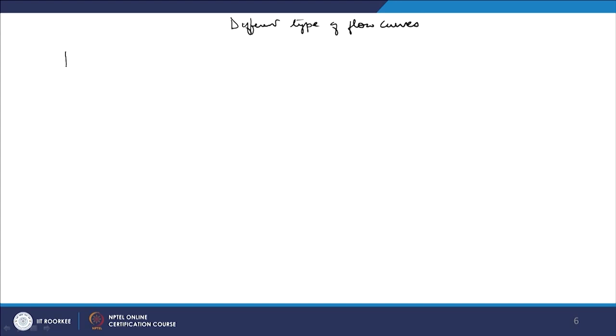So one we have already seen, at low temperature, sigma versus epsilon. You will have some elastic part, then plastic part, and then deformation and some fracture here. You can see that in this case the flow stress is continuously increasing as a function of strain. So this is what you will get usually at temperature lower than 0.4 TM. This kind of behavior you will always see, where you will only get the phenomenon we call work hardening.